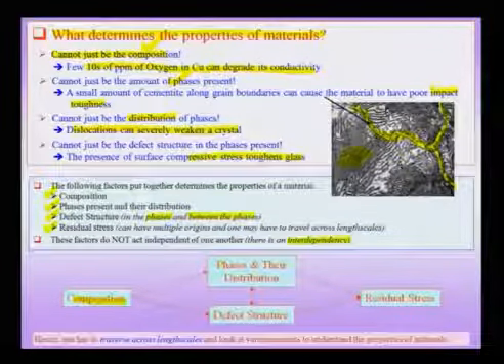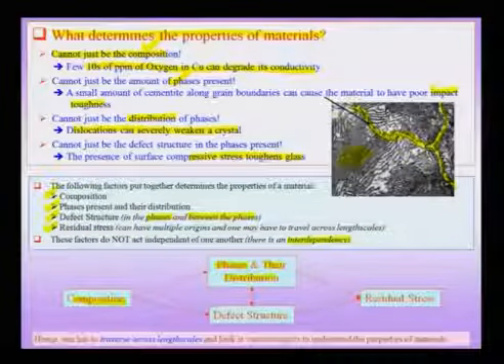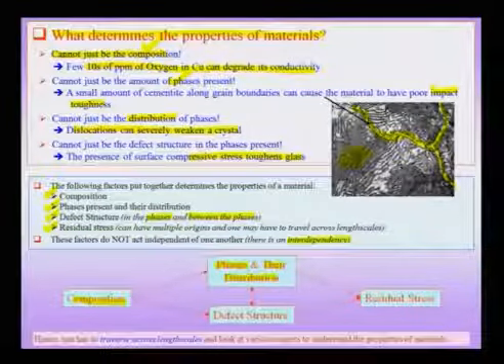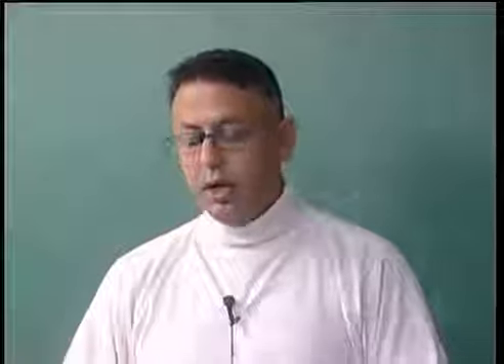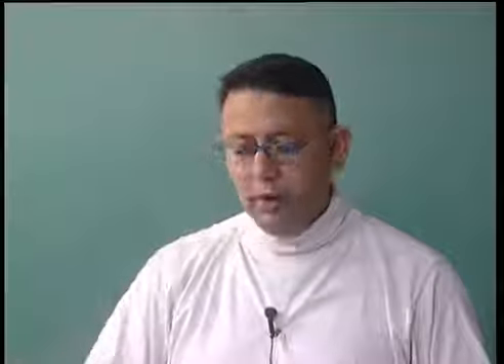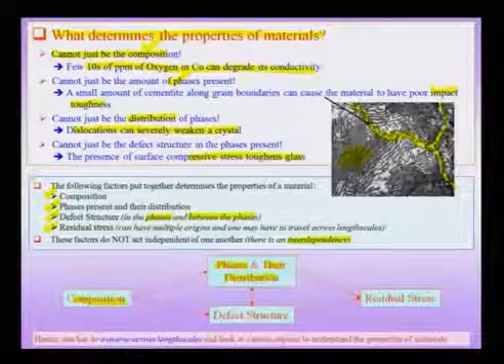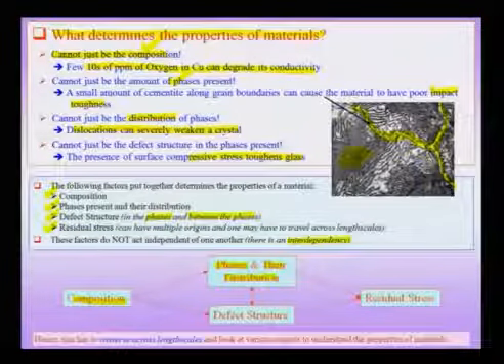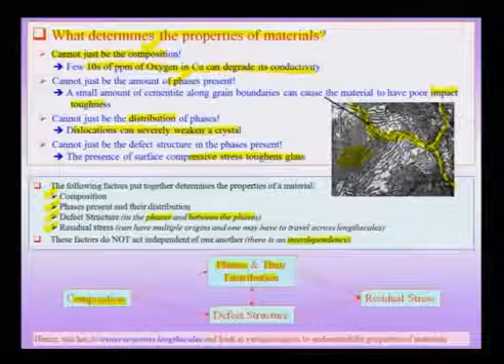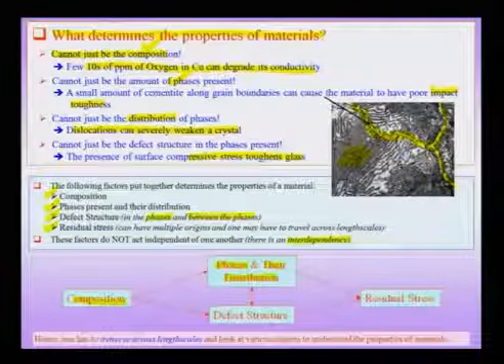I need to understand the phases present in the material and their distribution. We will also ask a question very soon: what do we mean by these phases, what kind of phases exist, and what kind of distributions can these phases be present in, and how this distribution of phases is going to determine the properties. One example, of course, we have already considered: if you have a second phase along a grain boundary which happens to be a brittle phase, then cracks under impact loading can propagate all along the grain boundary, and therefore, the overall fracture toughness of the material happens to be very low in spite of the fact that the second phase, as in the example considered above, was present in a very small volume fraction. It is the connectivity there along the grain boundary which gave it a poor impact toughness.